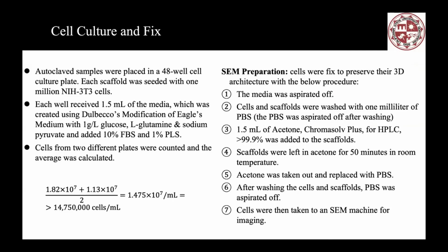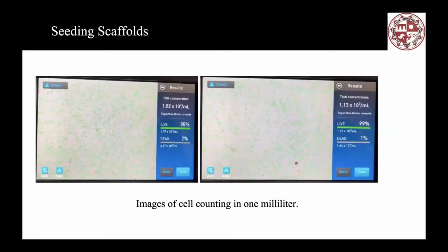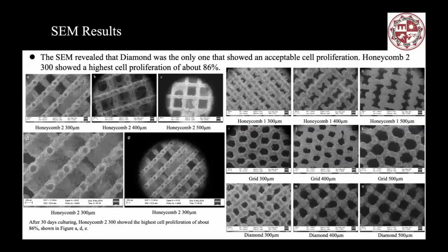Later on, after the compression test, we picked another 3 samples, and for each of them we used the cell culture and fix. So this is the procedure for our cell culture and fix, and then we tried to figure out whether the cells can survive in this scaffold. I think this process is more familiar to you, because we are from an engineering background, so we collaborated with Professor Jonathan Kelber in the biology department at CSUN. They helped us a lot with the cell culture and fix, and the later investigation. So here's the seeding scaffold. After we put the cells inside, we changed the medium every 3 days. Here is the cell counting in 1 milliliter, and these are some of the SEM results we got after 30 days of the culture.